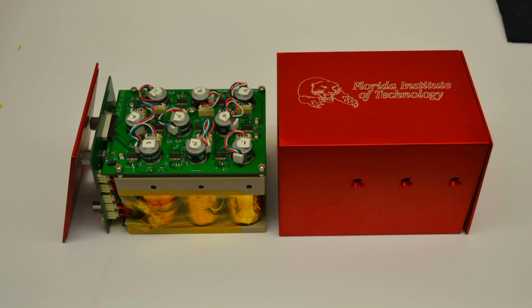One chamber is for the solution itself, and that's isolated from another little piston that has the protein powder in it. And when we get ready to start the incubation process, we run a little stepper motor that pushes the piston down into the vial and combines the protein powder with the buffer solution. So the incubation period starts. We also have to raise the temperature to 55 degrees in order for the incubation to occur, for the assembly of the fibers to occur.